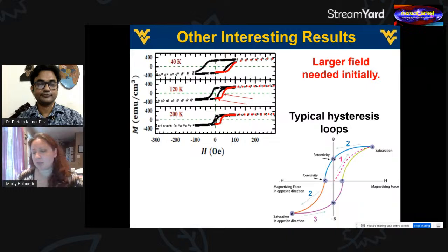So this is an interesting thing because this might be very relevant to many magnetic systems. People do these kinds of measurements on magnets all the time in industry, and they'll measure the width of these curves to understand how much magnetism they need to set a system. And what they often find in practice is that the magnetization that they need is sometimes a little bit bigger than what you would expect based on these laboratory measurements, what these black loops look like. So perhaps we have this effect going on, maybe not necessarily exactly the same effect, but a similar effect going on in many metallic systems.